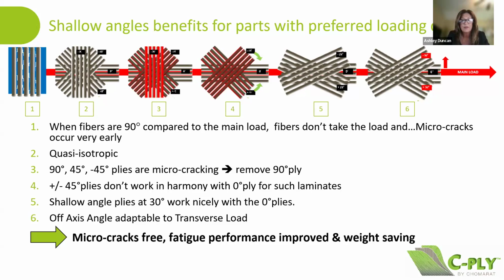The first laminate up in the left corner has fiber positioned 90 degrees compared to the main load. The fibers are not absorbing the load and microcracks can occur. And then the second laminate represents a quasi-isotropic stack. Again, not all fibers are absorbing the load. So in this series, stacks are removed to optimize fibers in the preferred load direction, but even plus or minus 45 degrees is still not quite optimized. So we have the ability to manufacture plies at 30 degrees, incorporating shallow angles in the preferred loading direction to improve part performance and reduce weight.